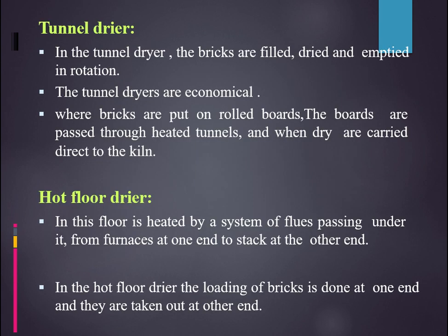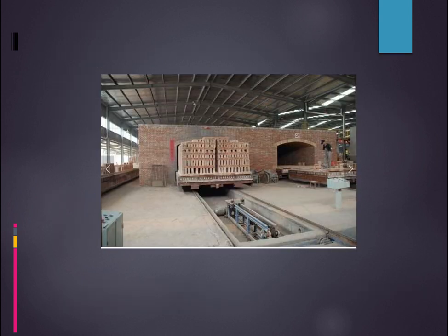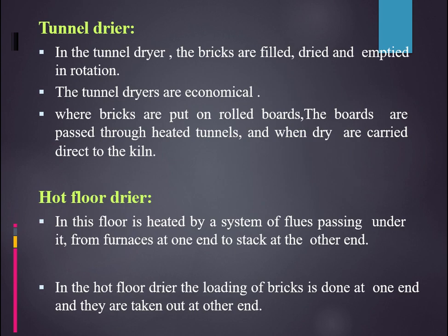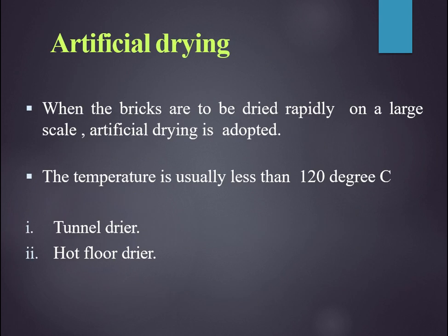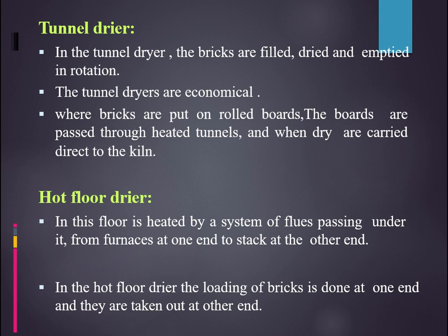So you can see here, we fill the bricks in layers and send the complete set of bricks through that tunnel, and the tunnel will be completely heated up, and once the bricks pass through that, they get dried. The base will have rollers, and once you move it, it will enter through the tunnel and come out. As told earlier, the temperature could be nearly around 120 degrees centigrade, and hence it will help in drying.